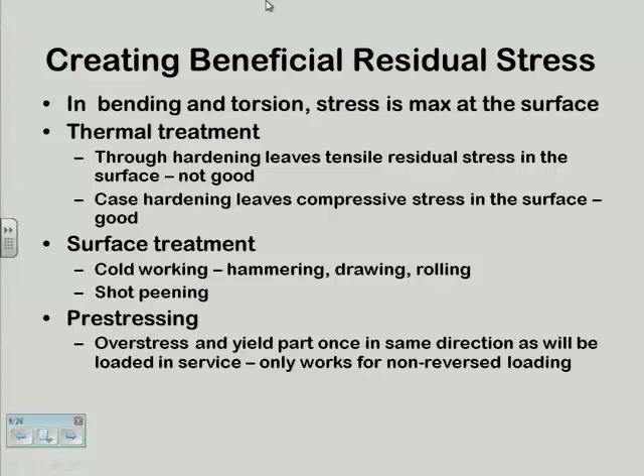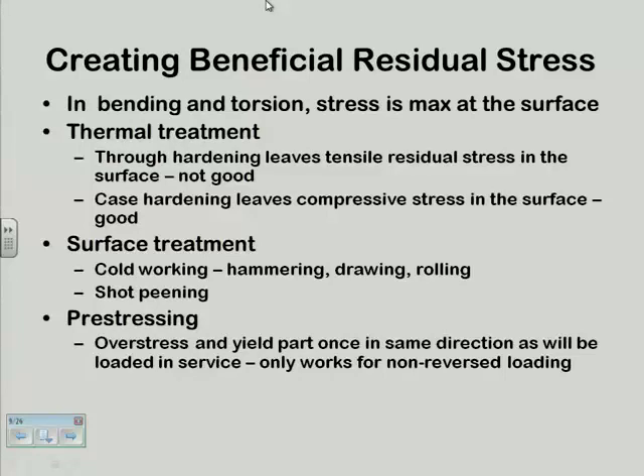When I case harden, I get a bonus: it leaves compressive stress in the surface. I heat the outside surface red hot — it expands. The cool core pulls back on it with tensile stress. Then I quench it and lock that in place: compressive stress locked into the shell, tensile stress in the core to balance it — equilibrium across the cross section. In bending or torsion the stresses are at the outer skin anyway, so I've protected where the stresses are high with compressive stress to lower that threshold.